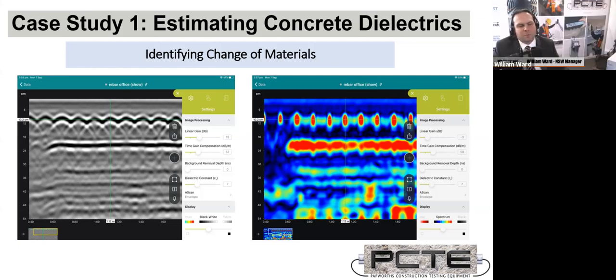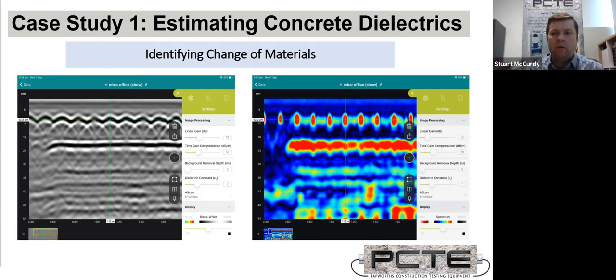Actually, the other interesting thing with Bondec is you can look like a second layer of rebar, because the ribbing of the Bondec coming up can look like point reflectors. So if you do have a Bondec slab, you may have a flat metal surface visible, but it's equally likely to look like a reasonably deep second layer of reinforcing. But everything above the Bondec would be fine. We just won't see past it.